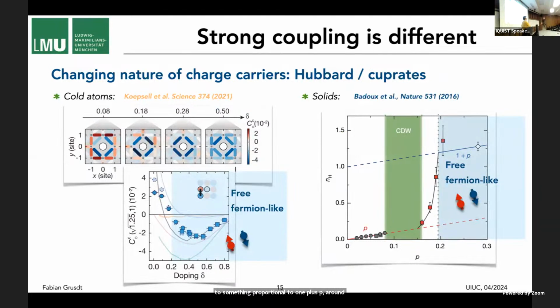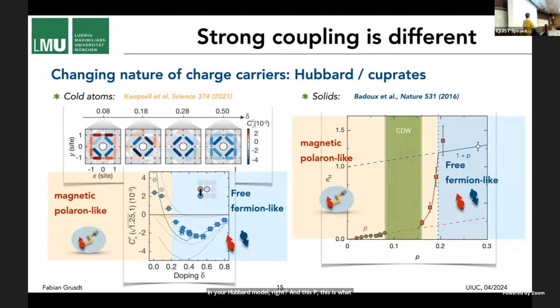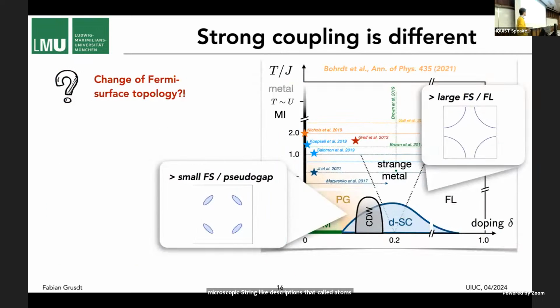And this 1 plus P, that's what you expect if you just had free fermions in your Hubbard model, right? And this P, this is what you expect if you have the charge carriers be individual hole excitations inside of the antiferromagnet, right? And the nice thing is this type of change from free fermion-like to what I call this magnetic polaron-like behavior, this also is something that cold atoms at the fairly high temperatures that they're at can really map out, and they see this happening around 20% doping, right? And this basically gives us some confidence that this microscopic string-like description that cold atoms could see signatures of at low doping actually works.